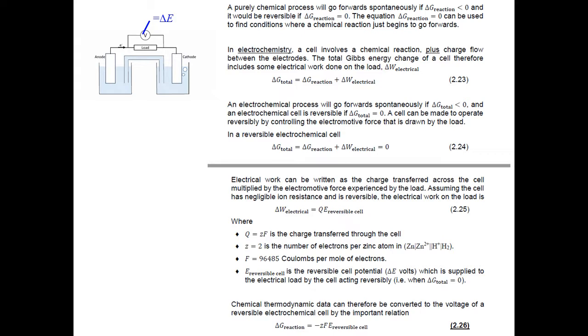We can use this equation 2.25 to identify this important thermodynamic term, so we get a very important relation, equation 2.26, which tells us that the Gibbs energy change of the reaction in the cell is equal to minus ZF, that charge, times the voltage, the E reversible cell. This allows us to tabulate E reversible cell.